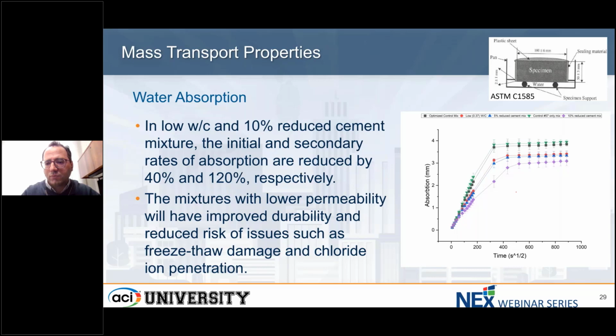But again, the performance we are seeing for that 10% low cement mix is better than any other mix, and the rate of absorption reduced by 40 to 120%, considering the initial absorption rate as well as the secondary one. So this means the permeability of the system, considering the water absorption and the bulk electrical resistivity, improves when we are using this optimized system, and that correlates to a lower risk when it's exposed to a freeze-thaw environment or chloride-induced corrosion.